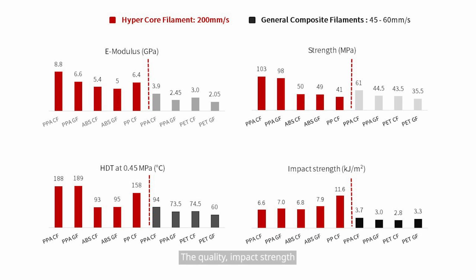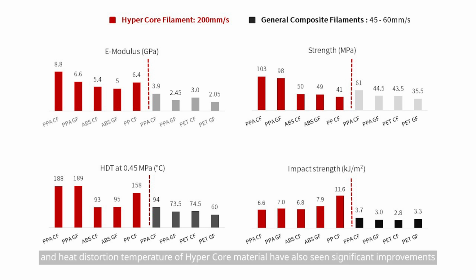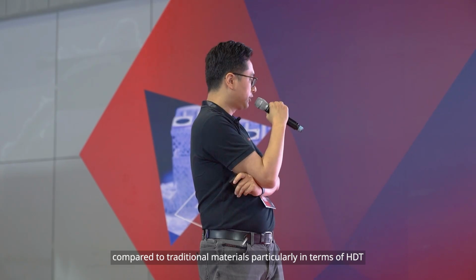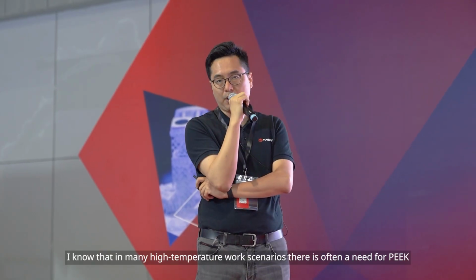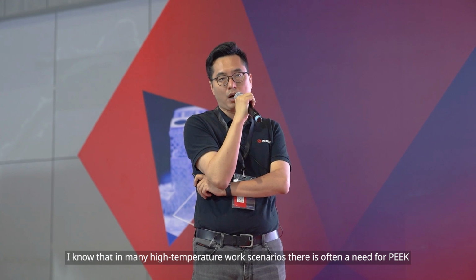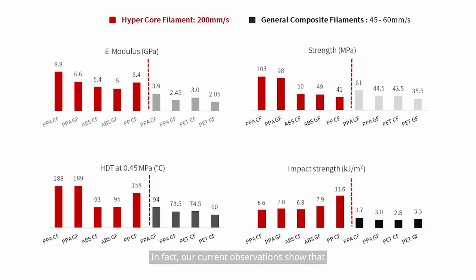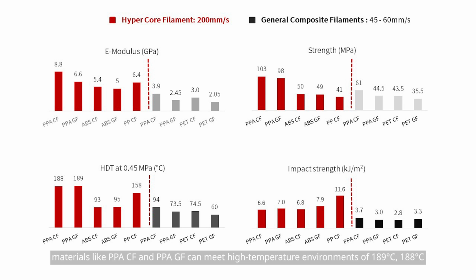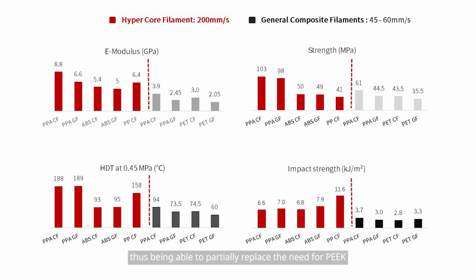The quality, impact strength, and heat distortion temperature of HyperCore material have also seen significant improvements compared to traditional materials, particularly in terms of HDT. I know that, in many high-temperature work scenarios, there is often a need for PEEK. In fact, our current observations show that materials like PPACF and PPAGF can meet high-temperature environments of 189 degrees Celsius, 188 degrees Celsius, thus being able to partially replace the need for PEEK.